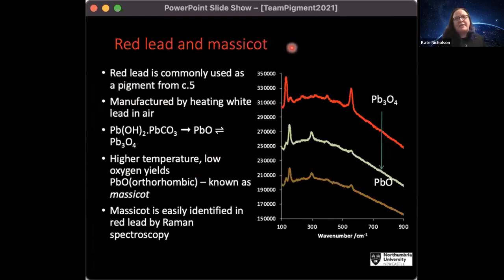The red lead pigment that's synthesized is obviously made from the lead sulfide, which is then turned into white lead, usually by burying in horse manure and urine for 6 months, so not a pleasant process. This white lead is then taken and put into an oven and roasted in air at precisely the right temperature, 585 degrees C. If they didn't get it so precise, and were out by plus or minus 5 to 10 degrees either way, you would get a chemically different form of lead oxide. And we could see that in the Raman spectra.